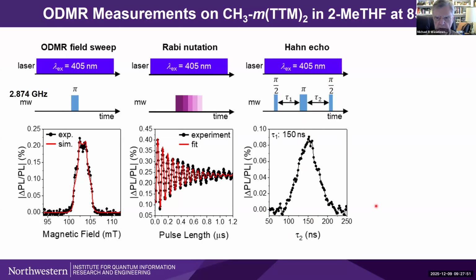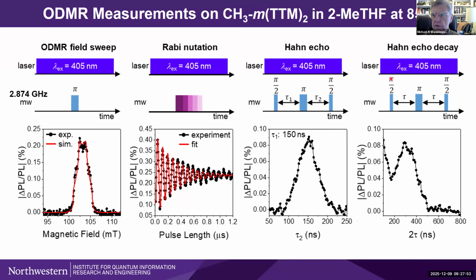And so it's a reasonably intense echo. Here's the other interesting thing. We can actually measure the TM value here too, but note the wild oscillations here. Those of you who do pulse EPR are aware of the fact that electron spin echo envelope modulation from the nuclei in the system is really very severe when you go to low frequencies. And that's what we're seeing here. We're seeing nuclear oscillations that are strongly damped in this particular system. And I'll show you another example coming up where we can eliminate this and get a pretty good TM value for this kind of system.